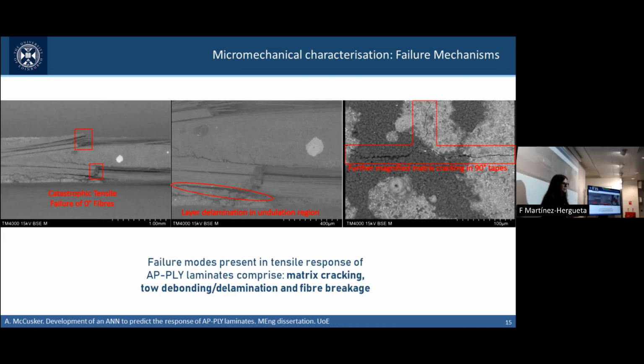This is not the same study. This was an MEng dissertation. It's not exactly the same laminate. It's missing a 90-degree layer on top and bottom. But these figures allow us to characterize further failure modes. We can see that the catastrophic failure occurs due to fiber tension, and it's at very specific points. If you analyze it by finite element analysis, it is clear that damage is triggered at points that have particularly large strains. There is a very large strain gradient originated.